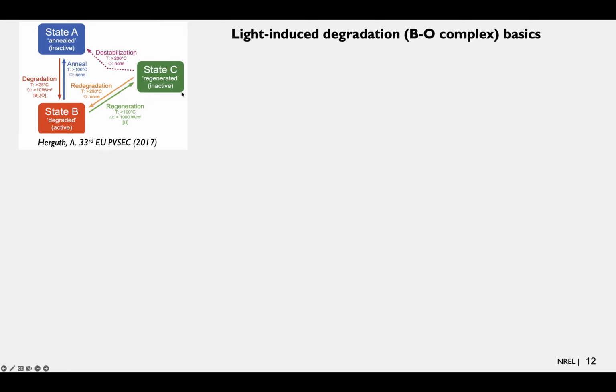Now the issue is that this so-called regenerated inactive state is fairly stable, but there are already known ways to destabilize it, and that's high temperature in the dark. So the models aren't exactly clear, or there's a little bit of discussion among experts about exactly how things work. But basically, if you put it at high temperature and with no light, you can get out of this C state and then lose power.